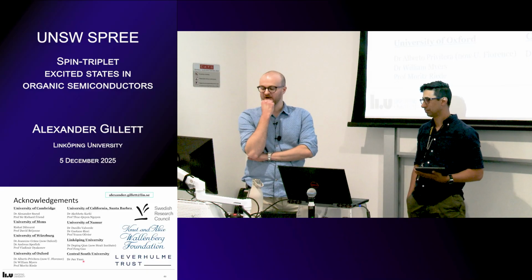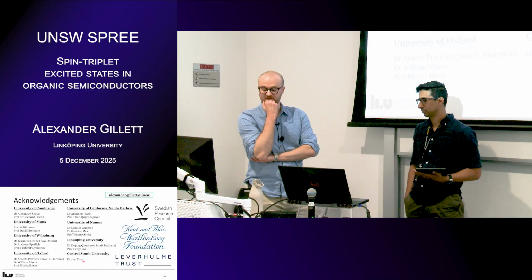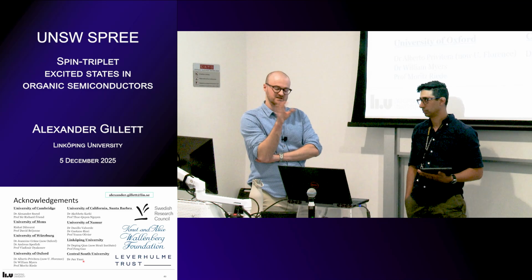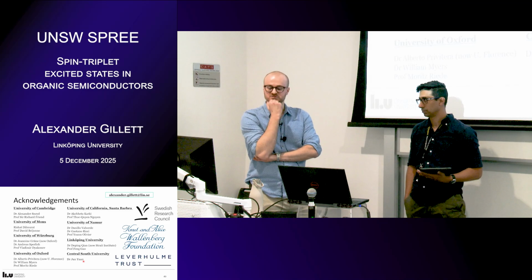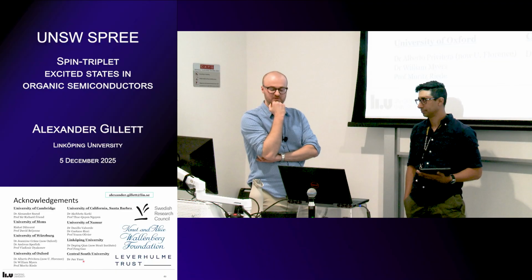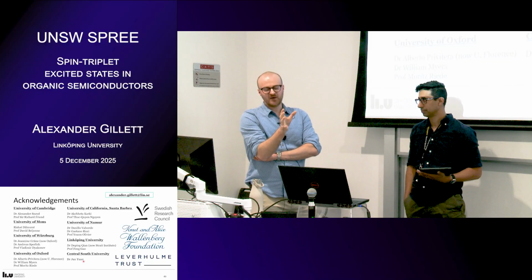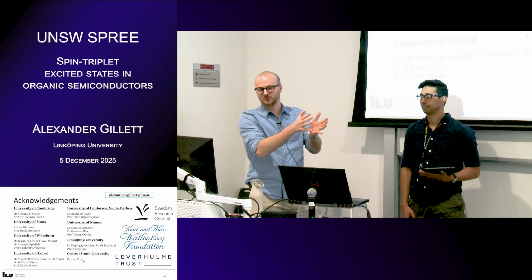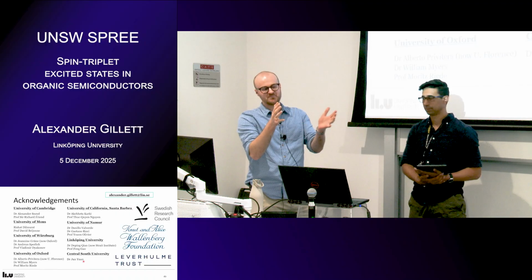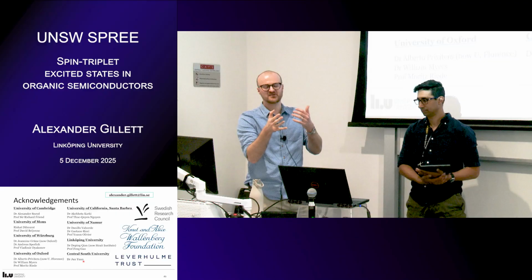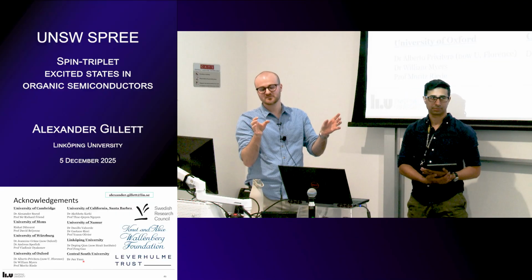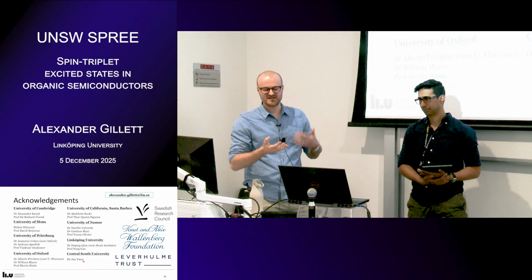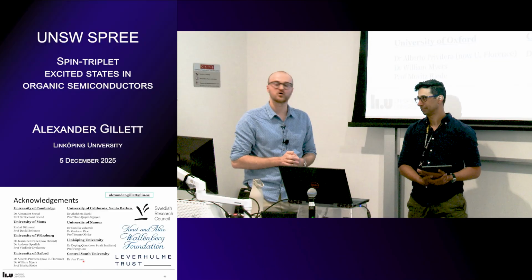Yeah, so there was a paper from the Cambridge group in Nature, I think last year or the year before, that I was somewhat involved with. I wasn't the lead person at all. But they found basically what you said, which is that in TADF molecules and some of the radical emitters, if you can separate the electron and hole, those high frequency modes, the CC stretches, are quite localized. They no longer modulate both electron and hole together and couple to the excitonic transition. They just modulate one or the other, and therefore they don't couple so strongly. And if they don't couple, they don't mediate non-radiative decay very well, and the PLQY goes up.